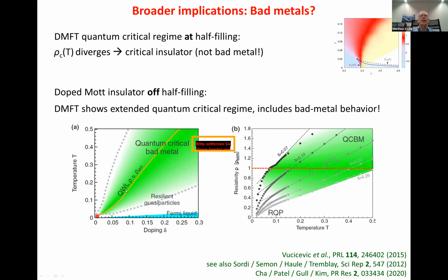And this happens in a regime here which, in this paper, has been attributed to quantum critical behavior. This orange line is labeled the quantum Widom line, a concept which appeared earlier in other papers, which essentially assigns an instability line to a first order transition. The Widom line continues this first order transition into the region of the phase diagram where there is only a crossover. Again, this bad metal regime is in a regime where there are no well-defined quasi-particles.